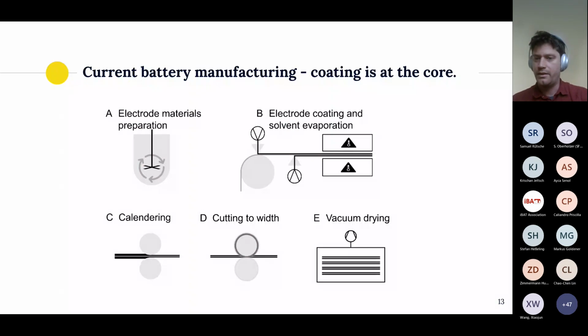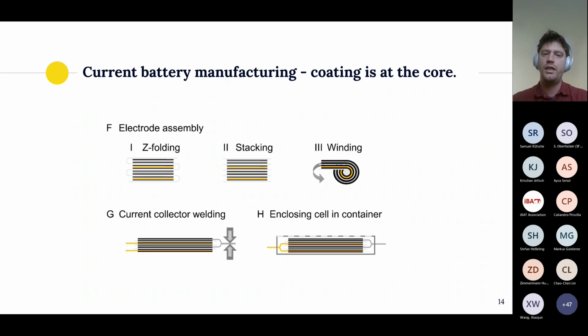If the solvent is evaporated in the subsequent drying station, you have a roll that can be calendared, that can be compressed to a desired thickness with the desired porosity. It's being shaped to the desired width and the desired length, depending on the cell format. It could be sheets, it could be daughter rolls for 18650 or 21700 cells. And then you get rid of the excess moisture in a vacuum drying step. You continue by assembling your cathode roll with the corresponding anode and the separator.